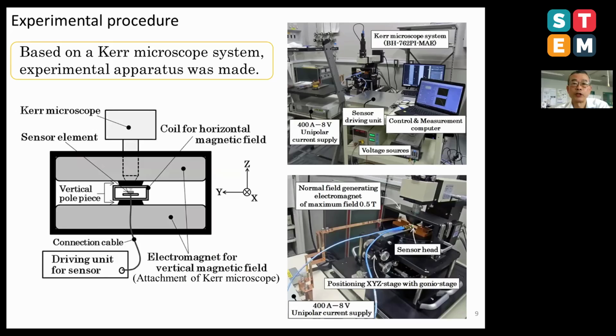This is a measurement apparatus I made for this study. For the purpose of confirming the tolerance against the normal magnetic field and also measuring the sensor property in the field, a measurement apparatus which can apply a strong vertical field was made. It was designed based on a Kerr microscope system. The vertical field was generated by an electromagnet, which was an attachment of the Kerr microscope. The sensor with driving circuit and the coil for controlling the horizontal magnetic field was set between the pole pieces of the vertical magnet. The single sensor was inserted with the sensor plane fit to the horizontal plane. The upper right photo shows a full view of the measurement system, and the lower right photo shows an enlarged view of the electromagnets and sensor fitted on the Kerr microscope.